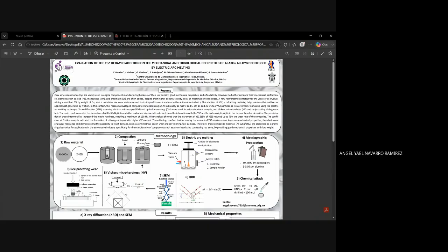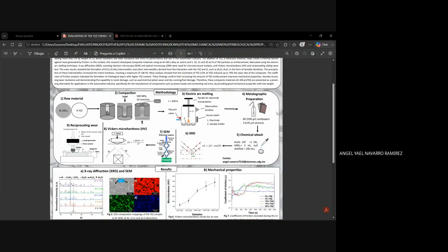The compacts passed to electric arc melting in an inert argon atmosphere. After the electric arc, they passed to metallographic preparation, done with grit sandpapers and alumina. Finished with that, I sectioned the sample into two parts. In one part I did a chemical attack with a reagent to reveal the microstructure and continued with analyses like XRD and SEM.